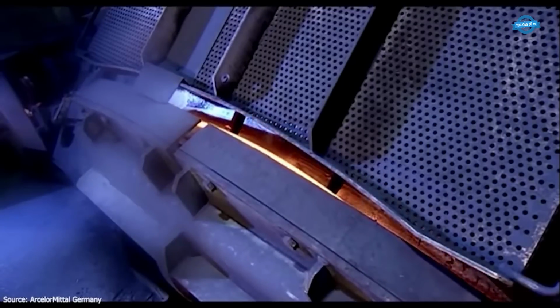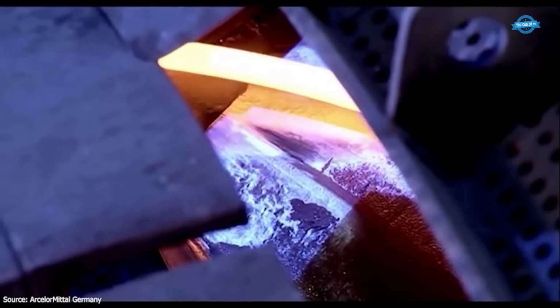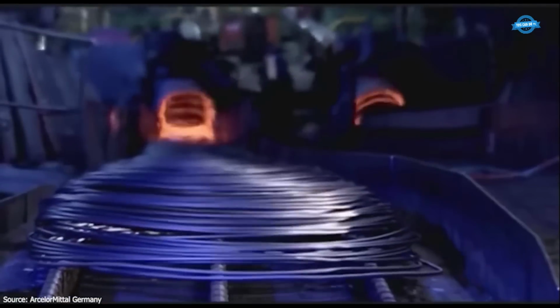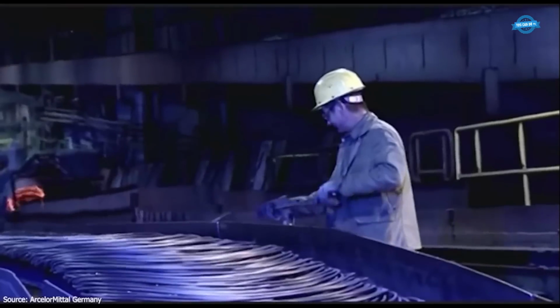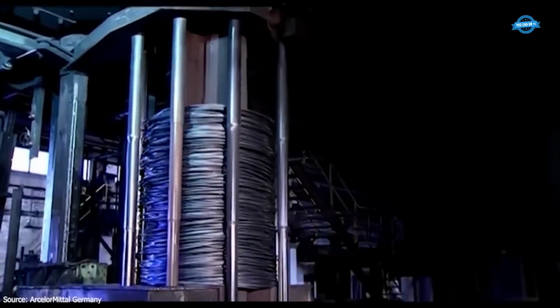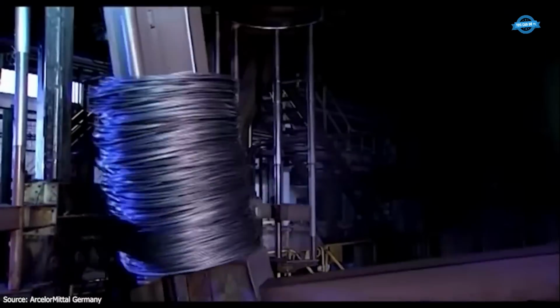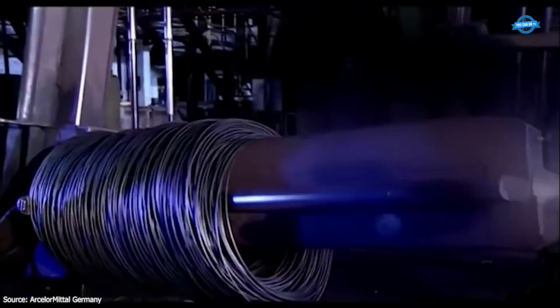After cooling, billets are reheated to over 1,000 degrees Celsius in the rolling mill. The rolling process reduces the billet diameter from 55 millimeters down to as little as 5.5 millimeters. The wire rod achieves speeds of up to 100 meters per second during rolling. Finished wire rods are coiled into bundles weighing approximately 1.5 tons.